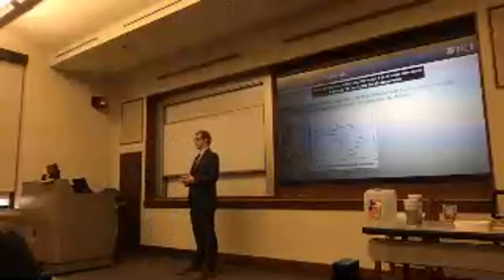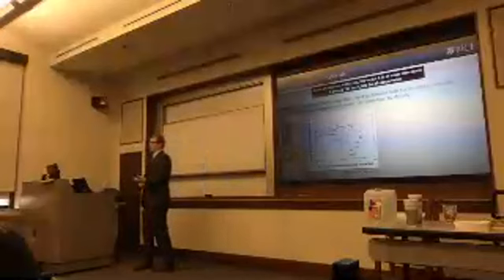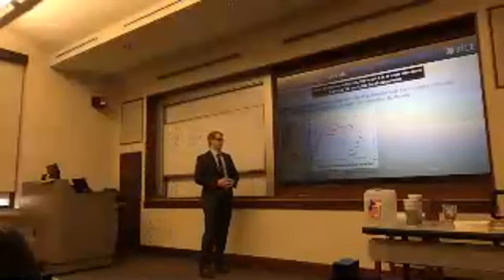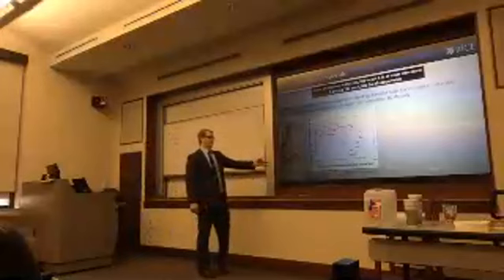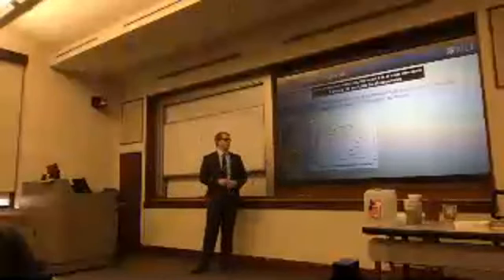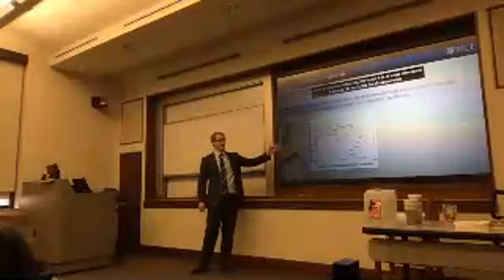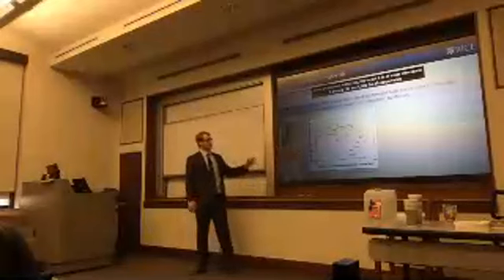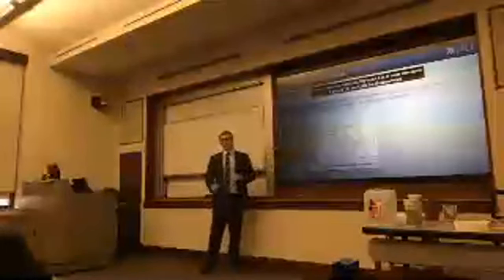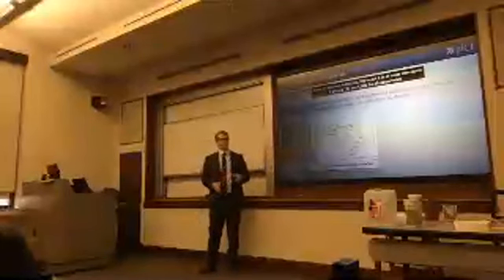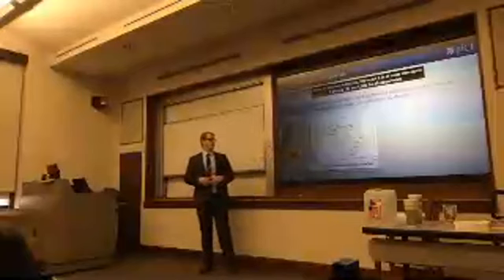Of course, carbon nanotubes have the potential of offering a lightweight alternative in terms of high strength and high electrical conductivity materials. And therefore, it's really important that we characterize properties of our fibers by normalizing them by their density. So here I'm showing a plot from a paper out of our lab in 2013 that shows the tensile strength and electrical conductivity normalized by the density for the fibers we were producing at that time relative to metals and carbon fibers. So you can see that our data is starting to push into this top right quadrant. And again, that's the goal of our research, to continue pushing to the top right so that we can outperform carbon fiber and metals on a per mass basis.